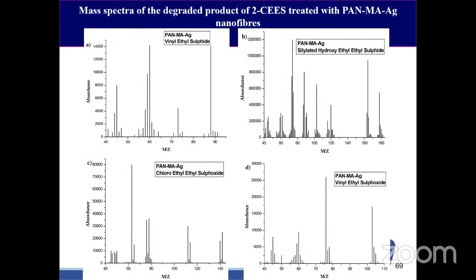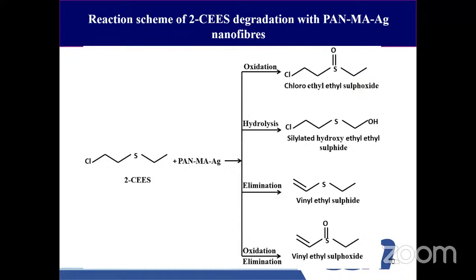And we have studied the degradation product. So the 2CES has been converted to something, and that degraded product has been analyzed by GCMS. What we found is the degradation products are vinyl ethyl sulfide, hydroxyethyl ethyl sulfide, chloroethyl ethyl sulfoxide, and vinyl ethyl sulfoxide. These are not as toxic as 2CES. So from the products, we identified the scheme of degradation of 2CES on interaction with magnesium aluminate. On oxidation, it forms chloroethyl ethyl sulfoxide. On hydrolysis, it gives hydroxyethyl ethyl sulfide. On elimination, it gives vinyl ethyl sulfide. On oxidation and elimination, it gave us vinyl ethyl sulfoxide.